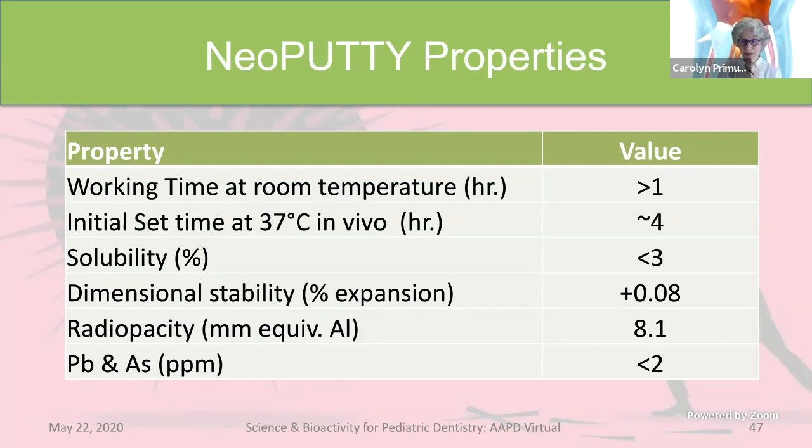So you put it in the body and it's going to require some time, about 4 hours in our ISO test method, to set. Once it sets, it's not soluble, it's stable, it's radiopaque, and of course, it's very pure, for those reasons that I mentioned that distinguish it from Portland cement, the construction grade.